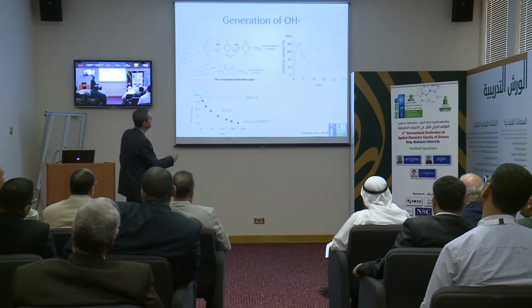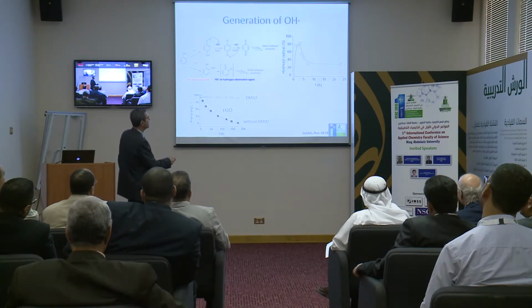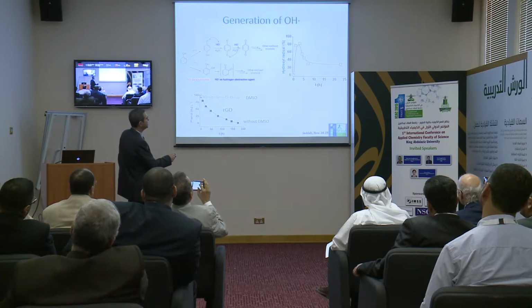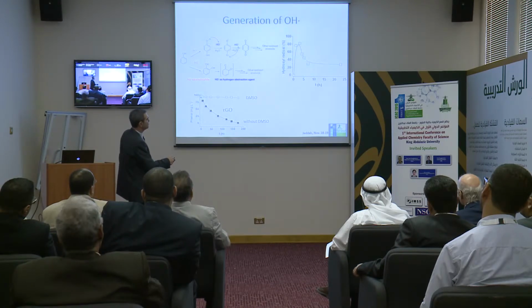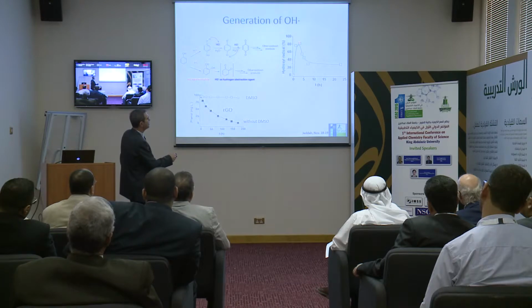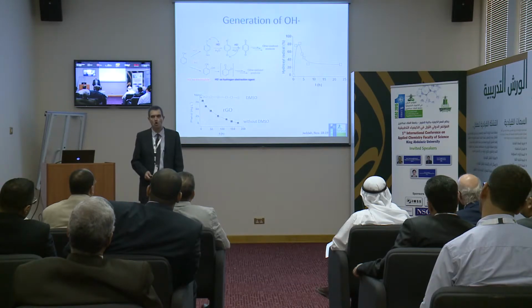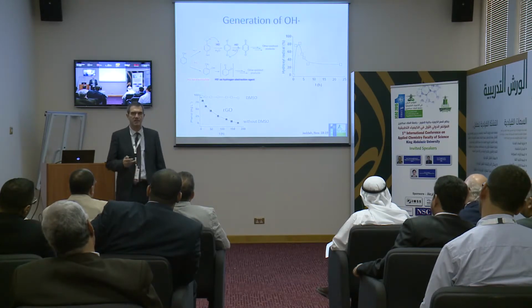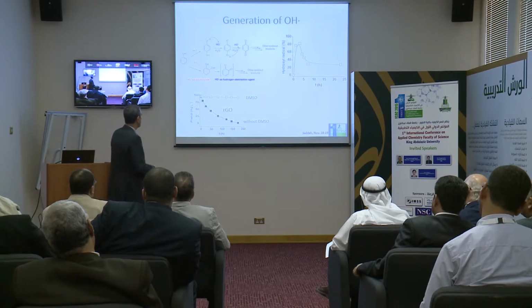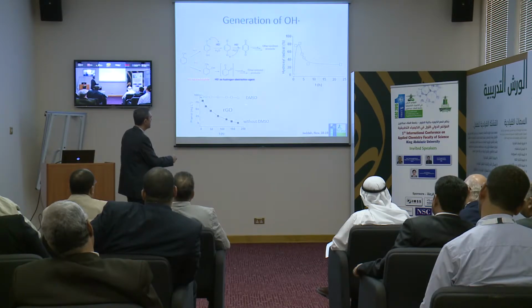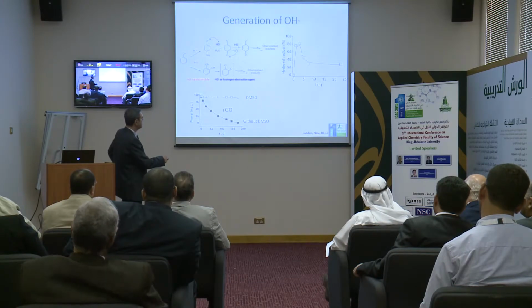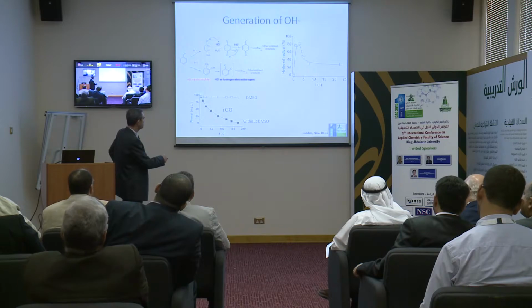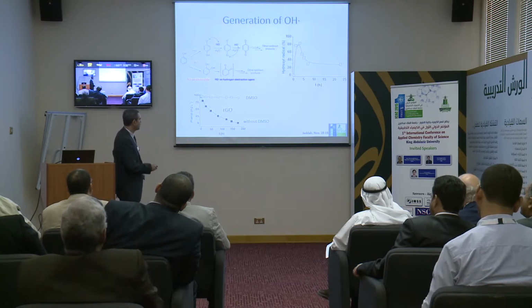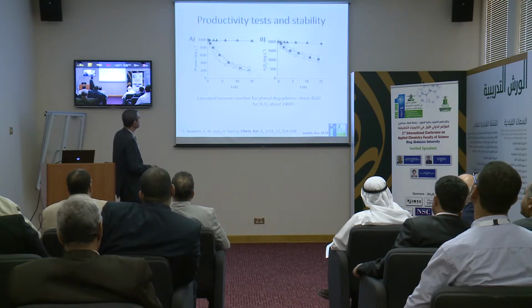We have determined the efficiency of hydroxyl radical generation, and this efficiency changes during the course of the reaction, but the top is about 80%: of the consumption of hydrogen peroxide, 80% is forming hydroxyl radicals. And we also have other indirect evidence, for instance, quenching with OH trapping agents like DMSO, and the reaction stops. This is without DMSO, the same reaction. In the presence of this hydroxyl radical quencher, the reaction stops.